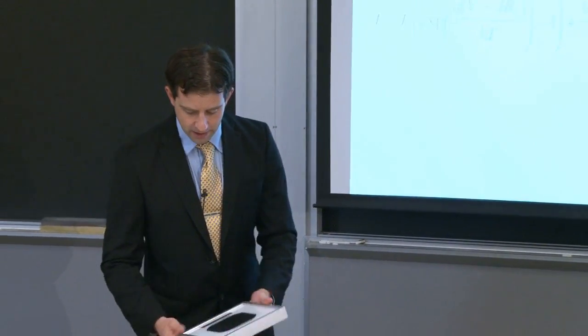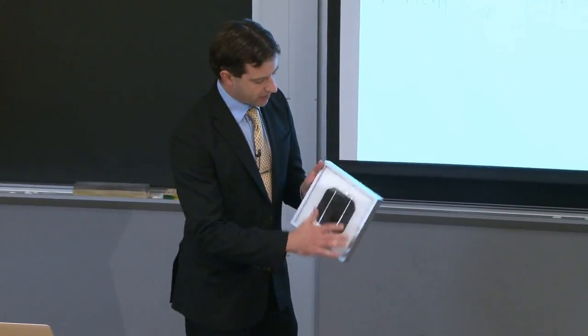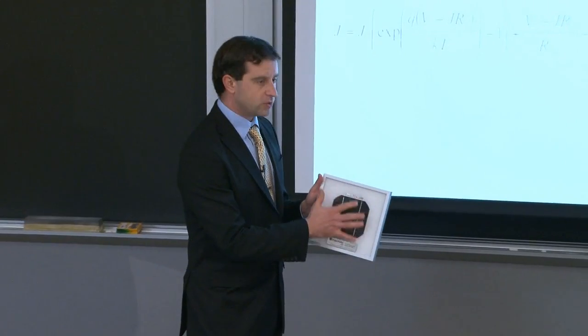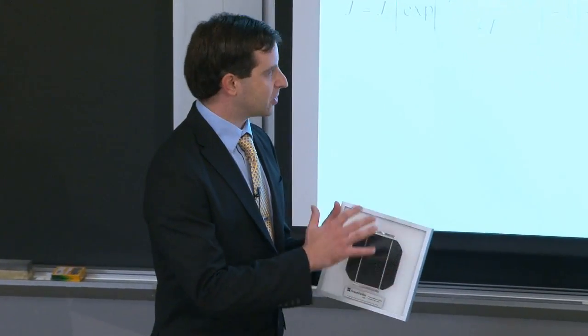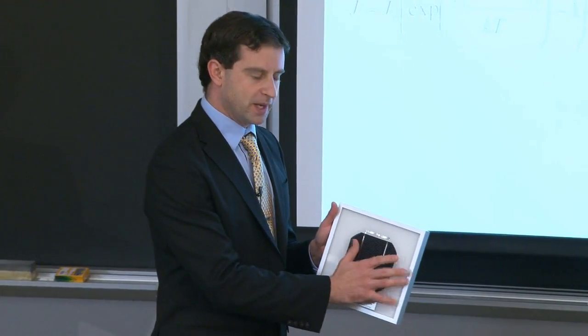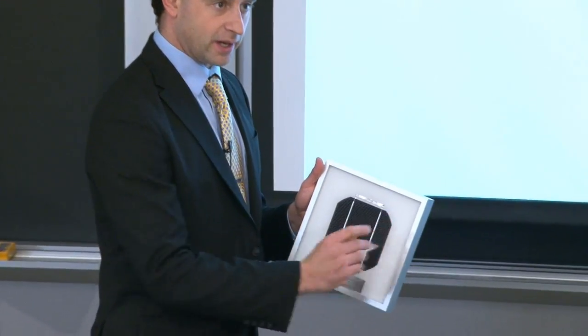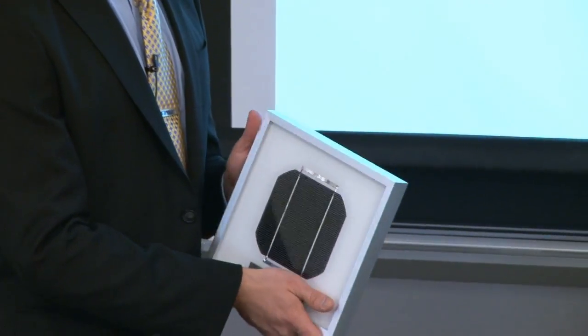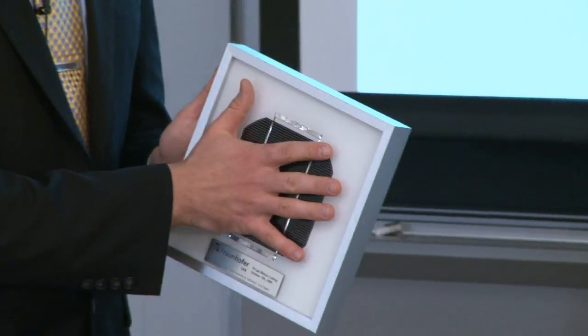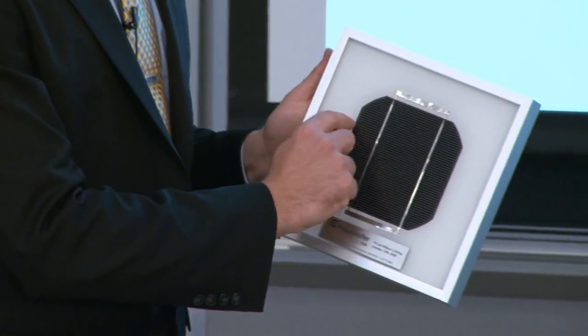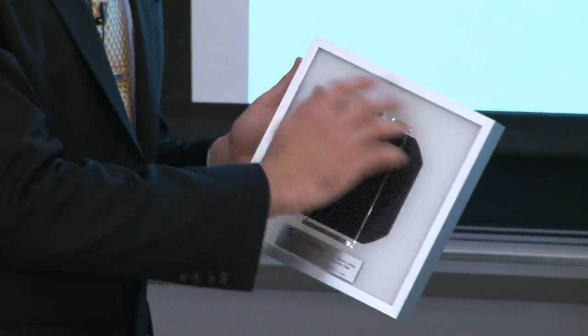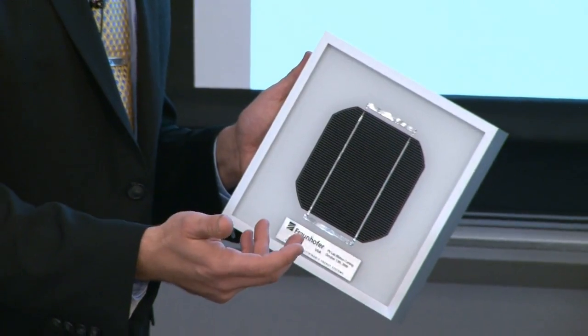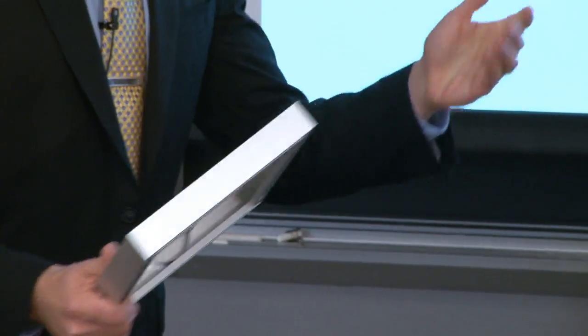On the low end, we might diffuse in the emitter very deeply to create a highly doped region everywhere, and then create a mask using not exactly a photolithography process. It could be a much simpler contacting process, and then etch away some of the emitter in other regions to make it more lightly doped. Or even in silicon's case, create a porous silicon layer and etch that off to distinguish between the heavily doped and the lightly doped regions.